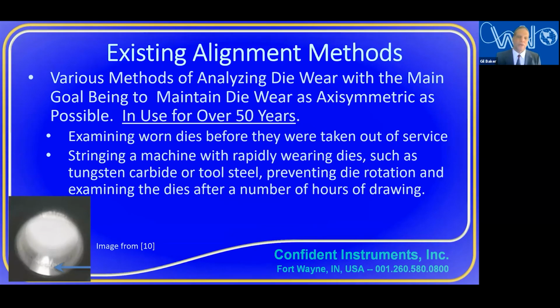Now, whether or not those dies were prevented from rotating through their service life, you'd have to ask someone else about that. But you definitely want to look at those dies coming out of service. Now, the second way this is used is you can string in a set of rapidly wearing dies. For example, most people are using various types of diamond dies nowadays. So if you put in a tungsten carbide die, it will wear much faster. Or you might even use tool steel to get a rapid wearing die.